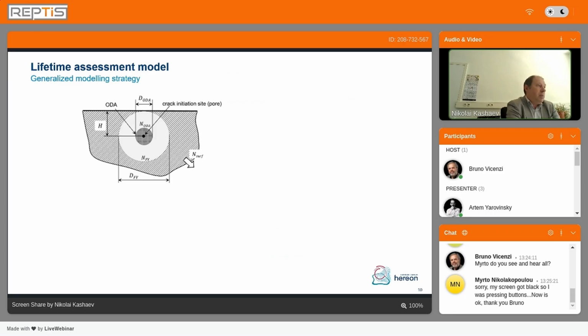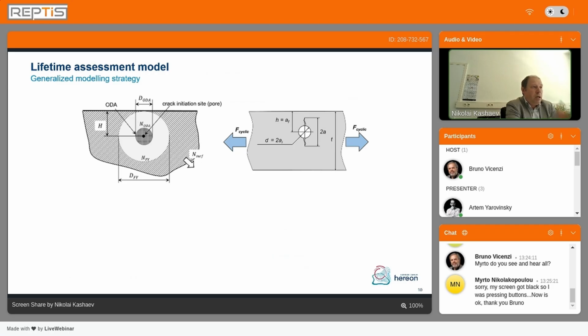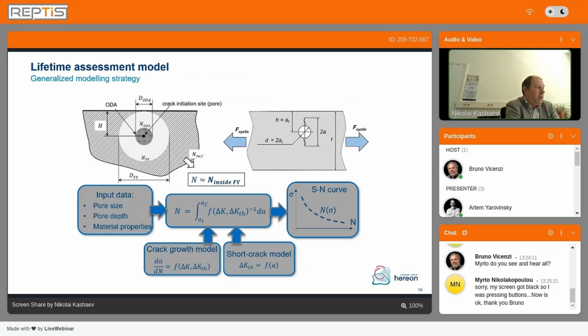In order to understand how we can model the fatigue behavior in principle, we have to understand schematically what our problem is. The problem is we have internal porosity, and from internal porosity we have the crack propagating to the surface. In principle, the assumption is that an internal pore can be considered as an already existing crack, and this crack propagates to the surface. If the crack meets the surface, the specimen or component fails.